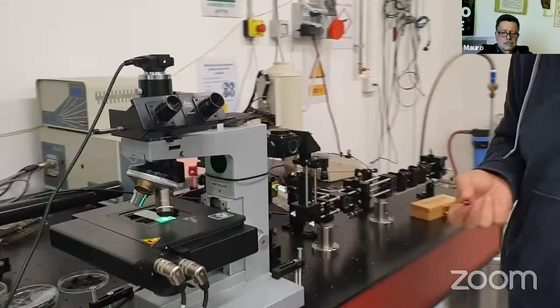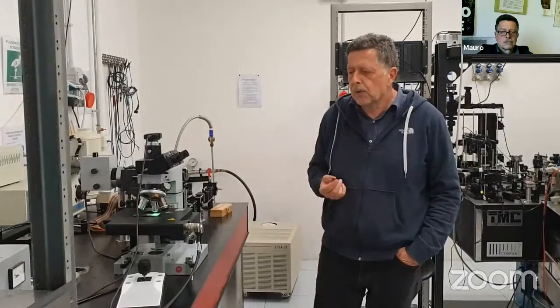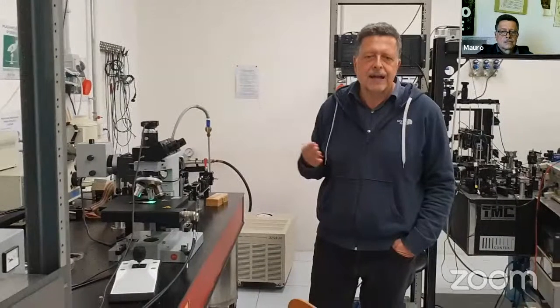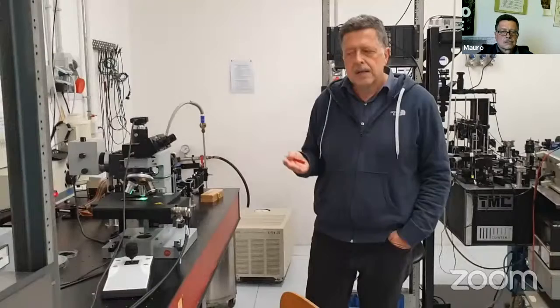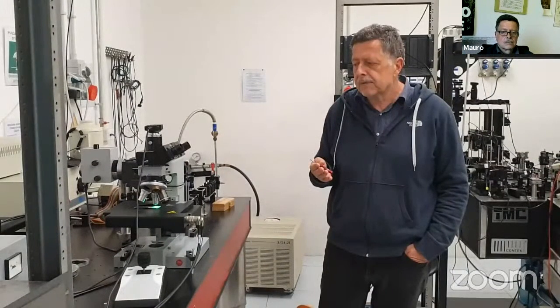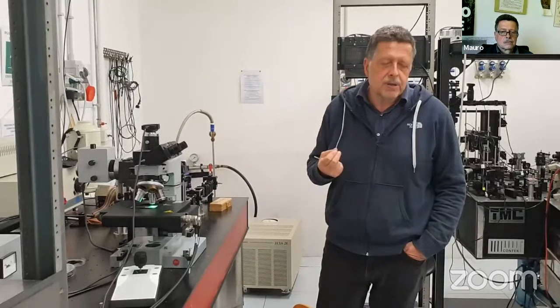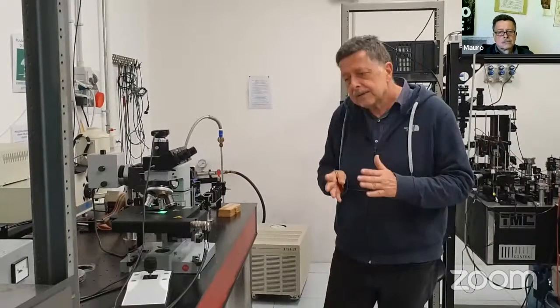Because, as you may know, the Raman cross-section increases with the excitation frequency to the fourth power. So you actually want to use a short wavelength laser. A green laser is more advantageous than a red laser. However, you also have a shortcoming, which is the possibility of exciting luminescence from the sample. When you have luminescence, you are in trouble because luminescence is very intense with respect to the Raman signal. The luminescence photons can cover the Raman photons, so you want to avoid luminescence. This is why for each sample you have to optimize the laser that you use. You have to use the shortest wavelength laser, but avoiding luminescence emission.